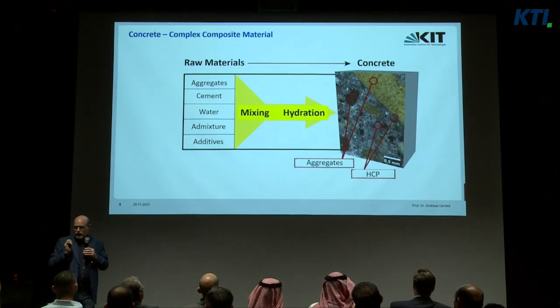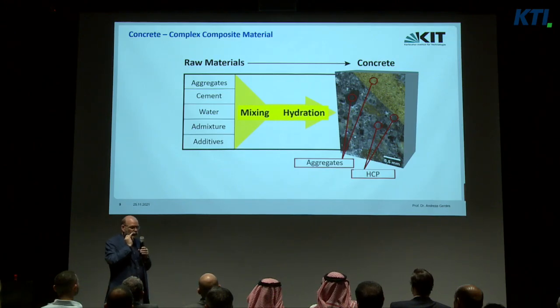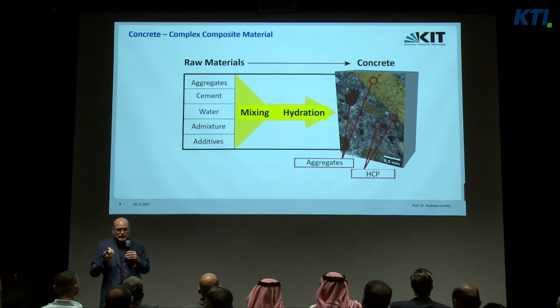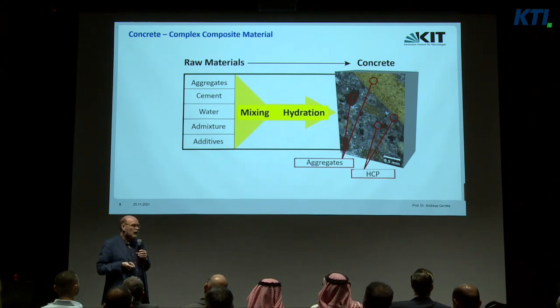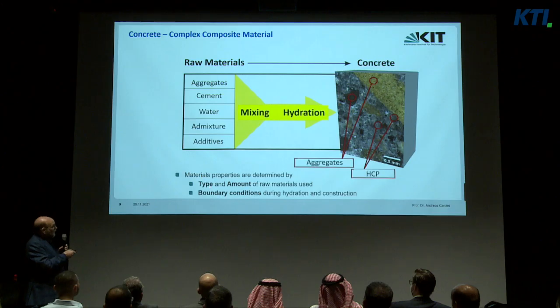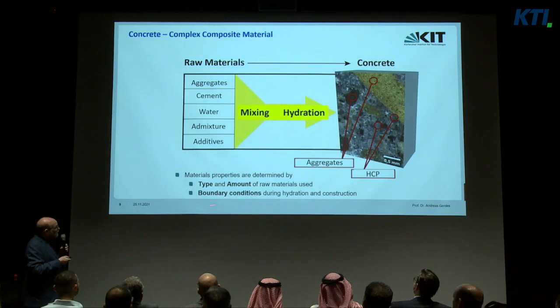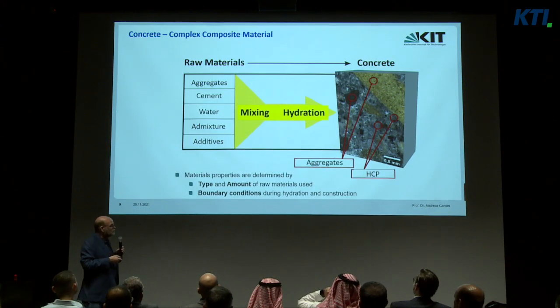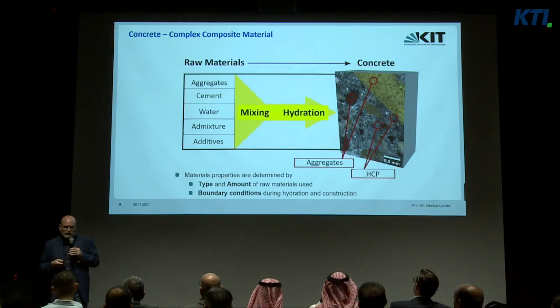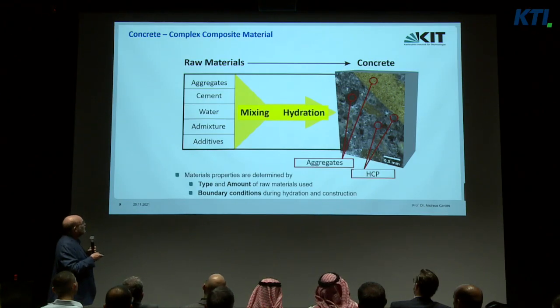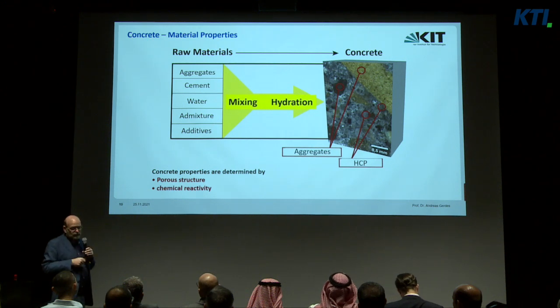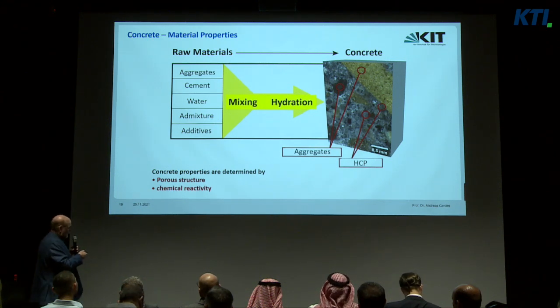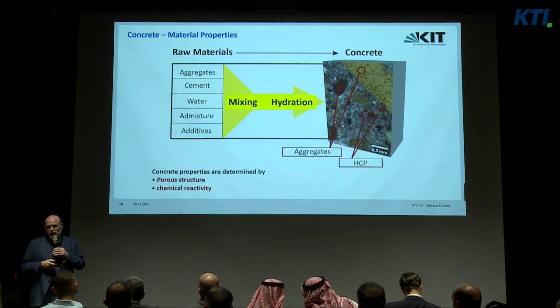However, so far we do not really know all the chemical reactions taking place during the hydration of the cements. But these hydration reactions determine the performance of the concrete, because the type and amount of raw materials used will influence the composition of this material. And the boundary conditions, like hydration or the construction phase, will also influence the performance of this material. But it's important to know the durability depends on the pore structure and the chemical reactivity.